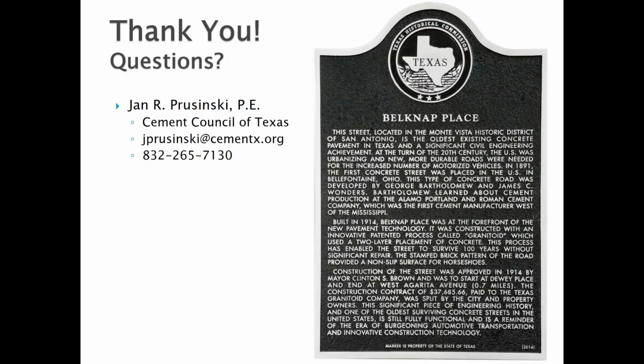And then what was the slump of each of the two layers, and was it changed due to weather or experience? The slump of the concrete was essentially no slump concrete. In the specifications, they reference tamping and compacting the concrete into place. So looking at the concrete and based upon the durability of the concrete, it was not placed as conventional concrete would be placed today. It was a very low slump or no slump concrete.